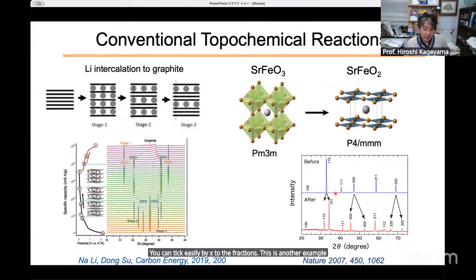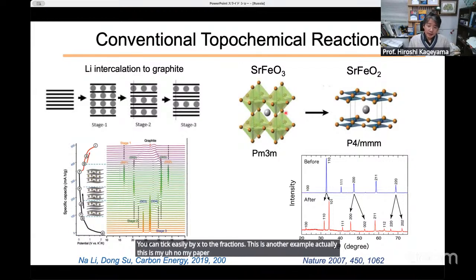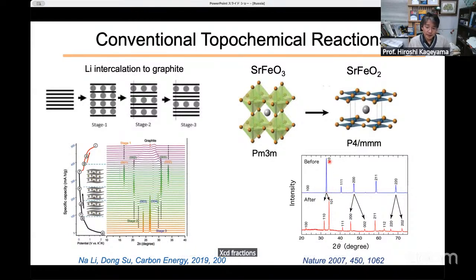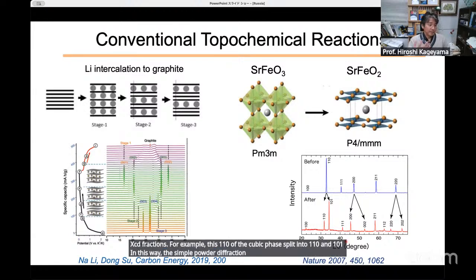Actually, this is my paper. Here, this perovskite structure changes into the so-called infinite layer structure. Here, that cubic to tetragonal phase transition can be easily detected by X-ray diffraction. For example, this 110 of the cubic phase splits into 110 and 101. In this way, simple powder diffraction can allow us to solve a crystal structure, which is very difficult in general in conventional materials. But with topochemical reactions, you are able to solve the crystal structure pretty easily.